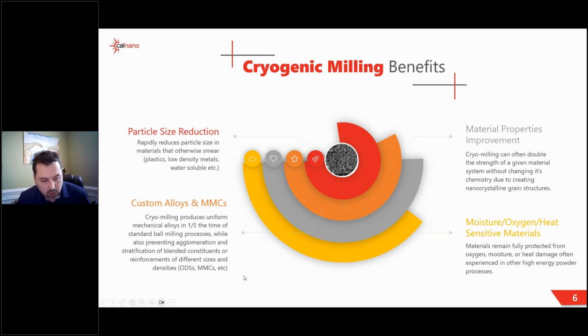And so we can really just create whatever type of chemistry with whatever kind of reinforcing particles you want, homogeneously blended very rapidly. And so the speed of iterations in developing that is very, very beneficial. And then you can always follow up with additional conventional thermomechanical processes or heat treating parameters to further optimize your material properties. And of course, last, very similar to the first one, which is moisture and heat sensitive materials.